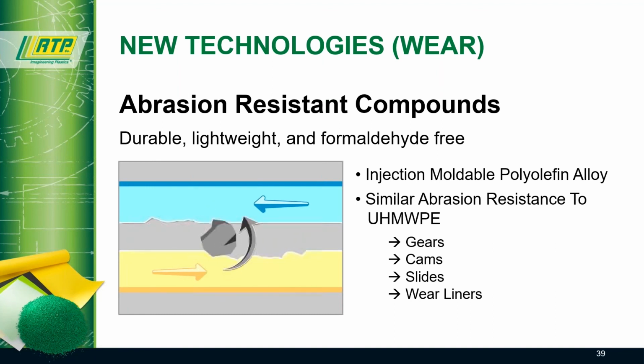The last area is wear. If debris gets into a system, it can cause catastrophic damage. Often, ultra-high molecular weight polyethylene is used because it is one of the most abrasion-resistant plastics. However, it's not injection moldable, so it is somewhat limited in its use. Parts must be machined out of a bar or rod stock, resulting in loss of productivity. RTP company tribologists have developed a polyolefin alloy that has similar abrasion resistance to the ultra-high molecular weight polyethylene, but it is injection moldable. This opens up a lot of options for abrasion-resistant part design. And that just gives us a small slice of the many technologies we continue to work on at RTP.